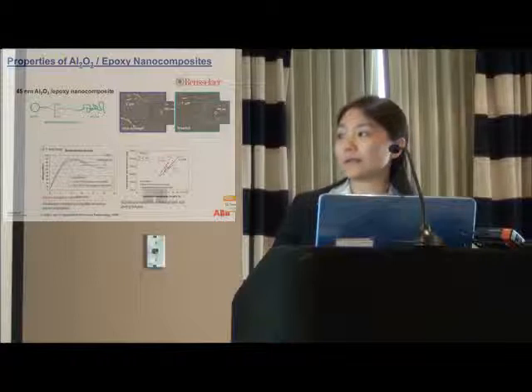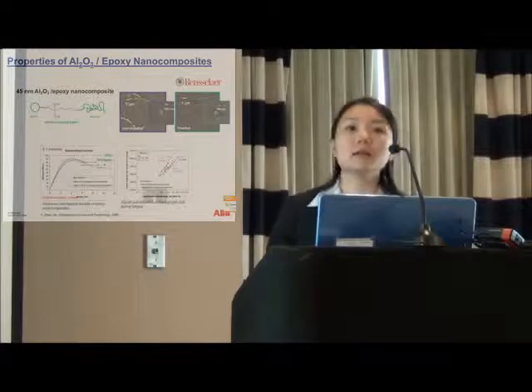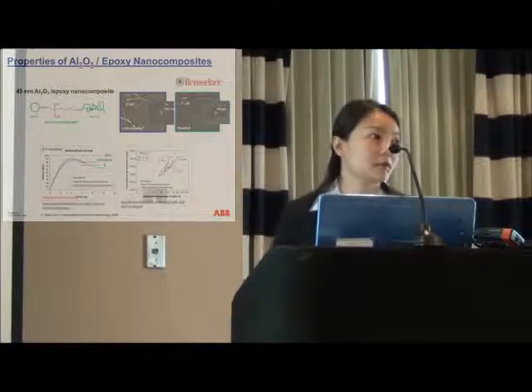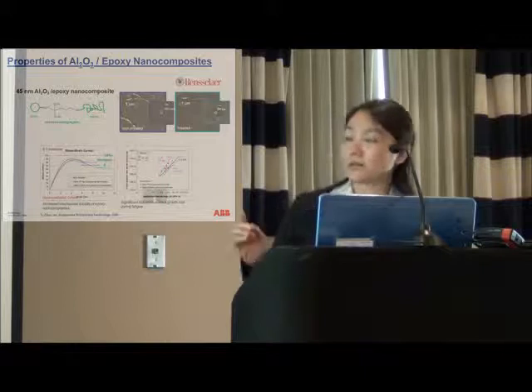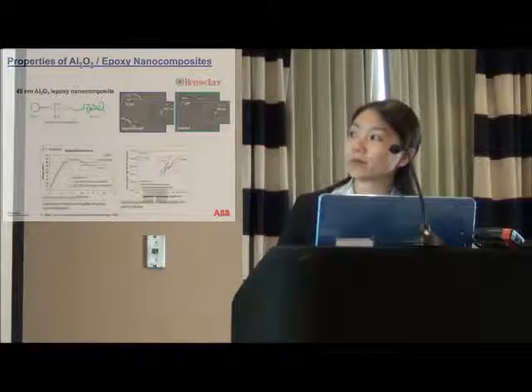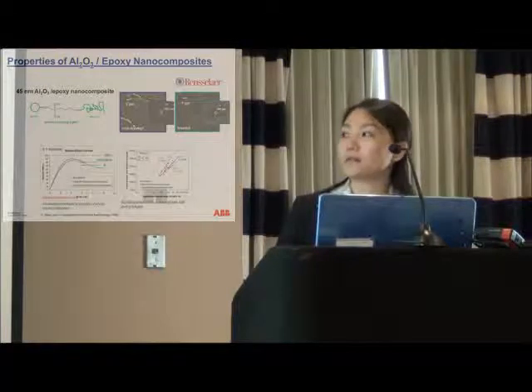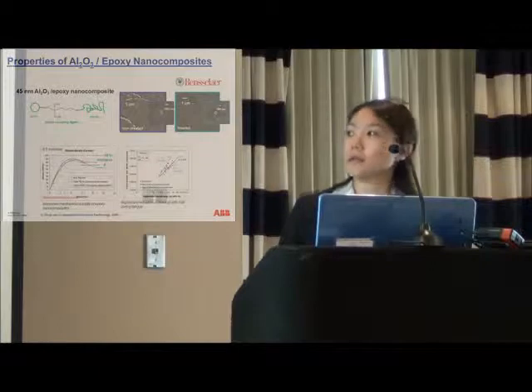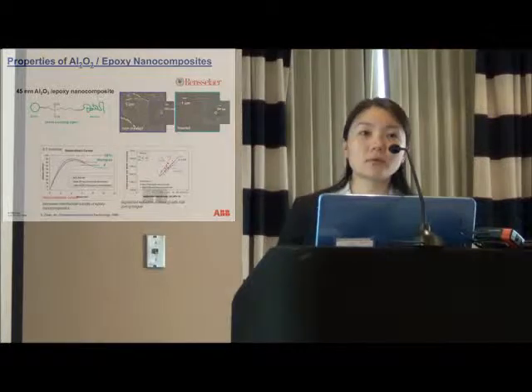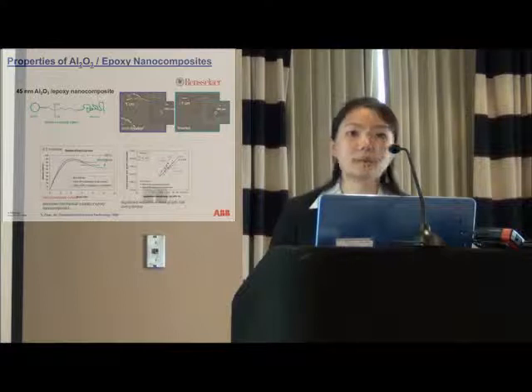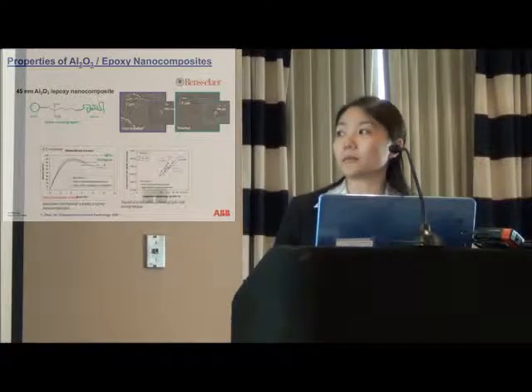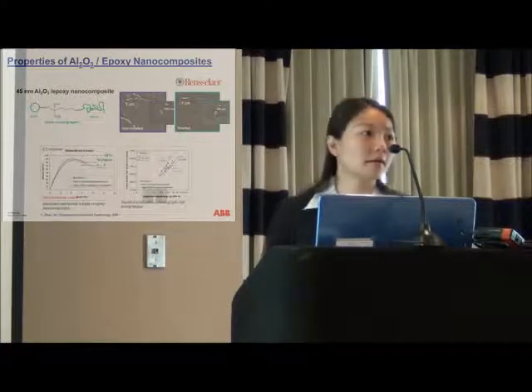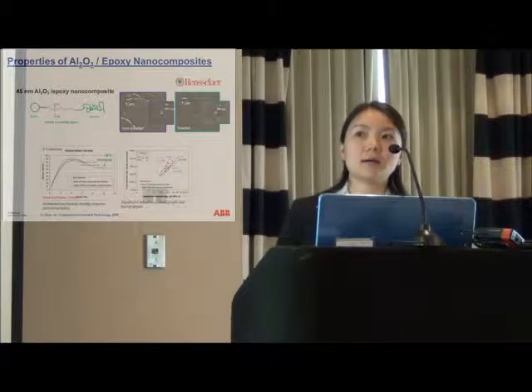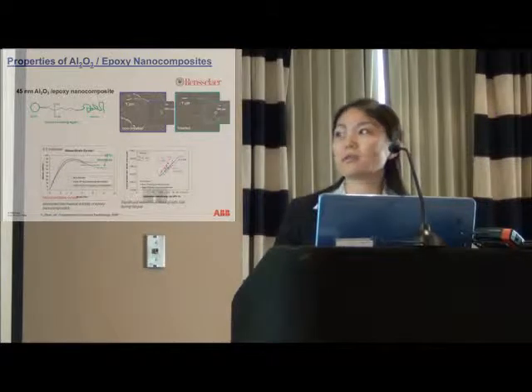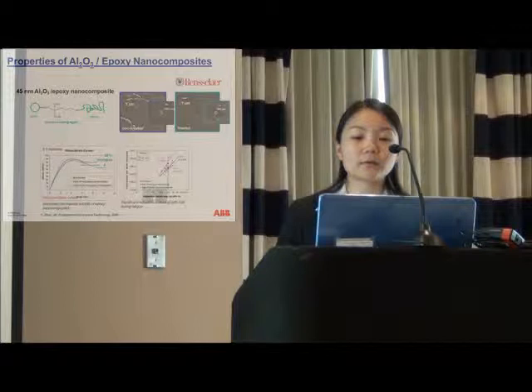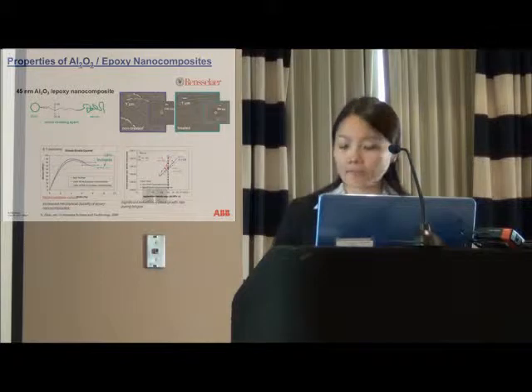If we draw this line and assume we apply the same stress concentration factor on all three materials - the pink one is the neat polymer, and the other two are the nanocomposites - the crack growth rate of the nanocomposite dropped significantly compared to the neat polymer, about one order of magnitude. That means by adding nanoparticles, you significantly reduce the crack growth rate in the fatigue test.